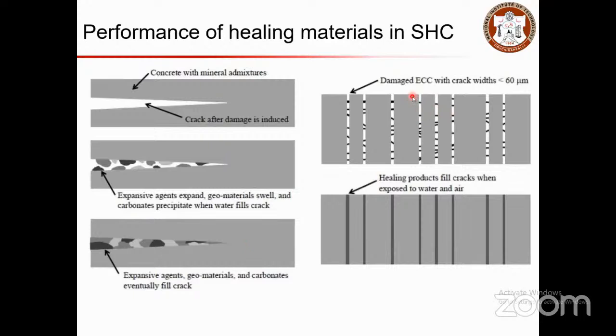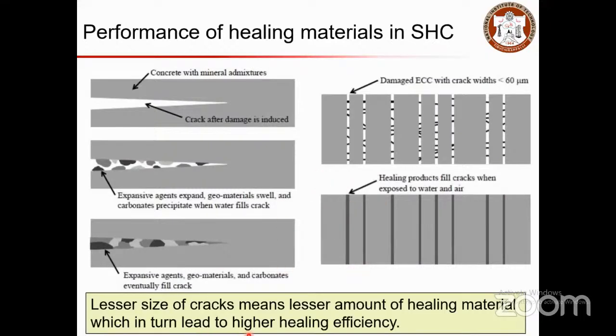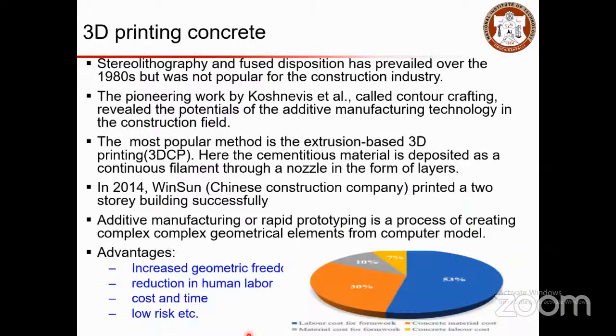Right. Similarly, here you have damaged ECC with cracks less than 60 micrometers. In this case, you have a healing product that would fill up the cracks when it is exposed to water and air, and this is how your structure is going to look. The lesser size of cracks means a lesser amount of healing material is required, which in turn gives higher healing efficiency. So the self-healing concrete concept works better when you have smaller cracks, and over time the smaller cracks will be controlled, which helps to prevent crack growth or severe crack formation for that reason. Right? So what is the latest technology that we use?